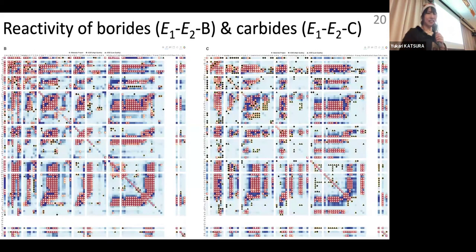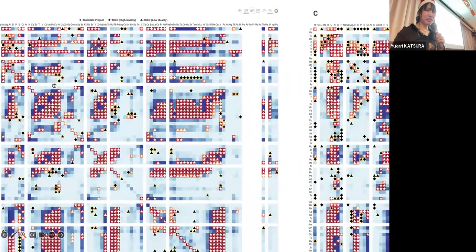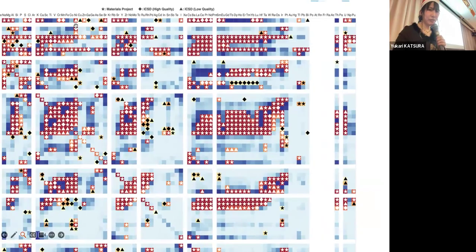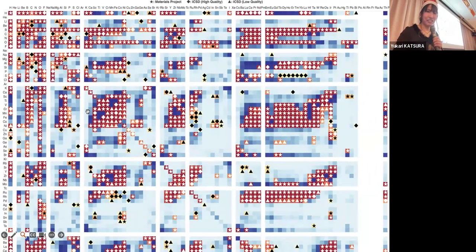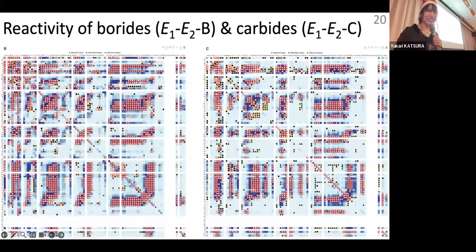Okay, let's see the reactivities. We kept improving the learning algorithms, and now I was very satisfied with this map. In the borides, it was important to show this boundary. Nickel reacts with boron, but copper doesn't react with boron. And this boundary was clearly shown in this map, so I really liked this map. We can see the many dark blue grids, so we can try to synthesize these promising compositions.